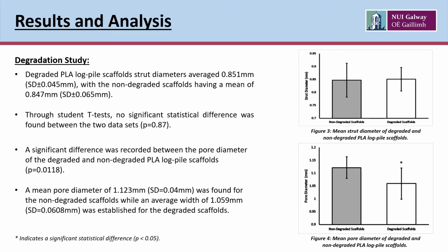The difference between strut width and pore size before degradation and after degradation is shown in this slide. The strut width remained fairly constant over the course of the degradation process, whereas the pore size decreased significantly over the 7 days in sodium hydroxide.